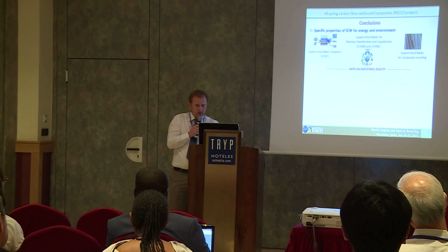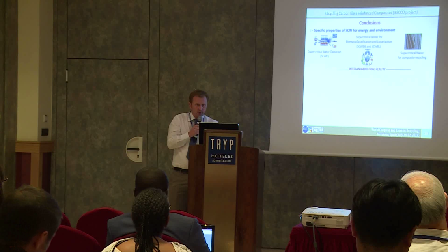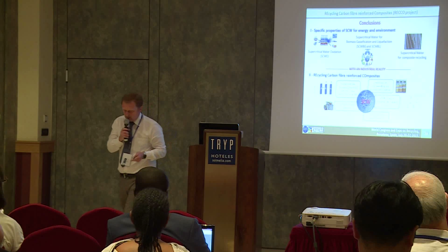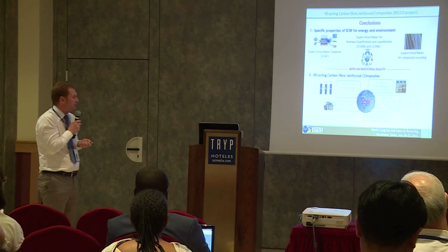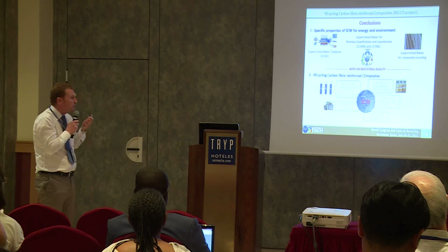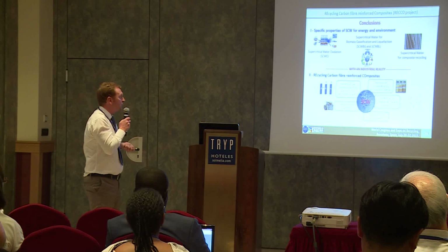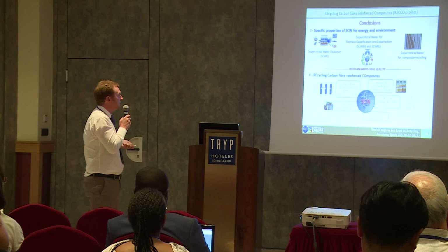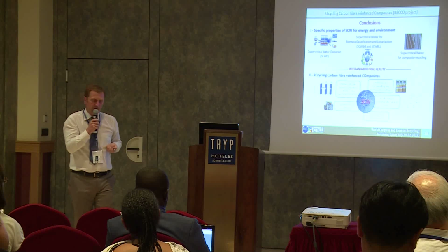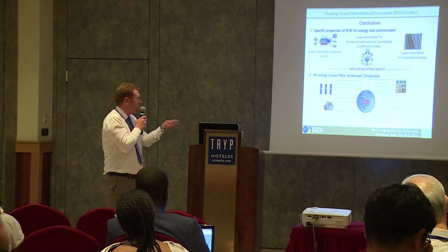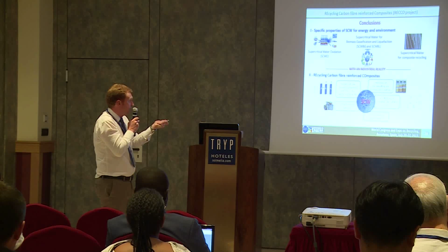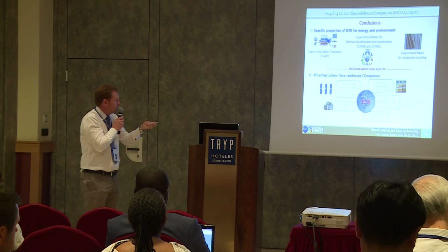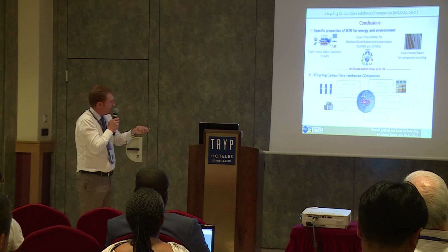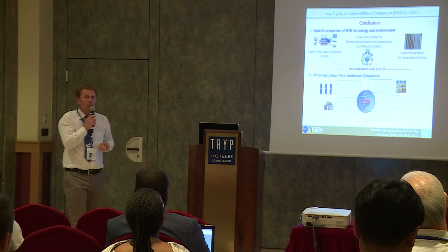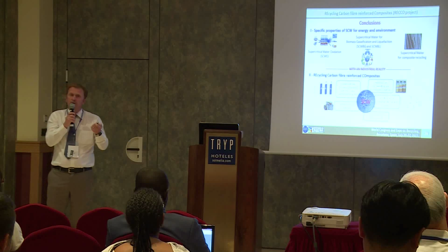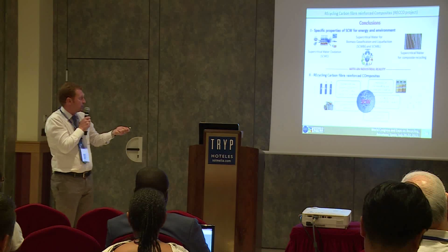So as a conclusion, I spoke about the properties of supercritical fluids. I showed that this can be, I say this can be, because I'm convinced that there is not a unique solution, but this solution could be one solution for the recycling of carbon fiber from carbon fiber reinforced polymers. You have seen we can recover clean fibers through hydrolysis, a very interesting alternative to pyrolysis when you are looking at the evolution of mechanical properties before and after treatment.